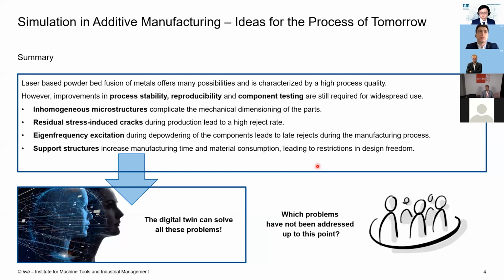In regard to the process simulation, we would like to use the digital twin to address the most challenging topics, for example, here, the inhomogeneous microstructures, which is complicated for the mechanical dimensioning of the parts. Also the residual stress-induced cracks during the production, which lead to a high reject rate, and also the eigenfrequency excitation, which also leads to the fact that we cannot use these parts for further applications.